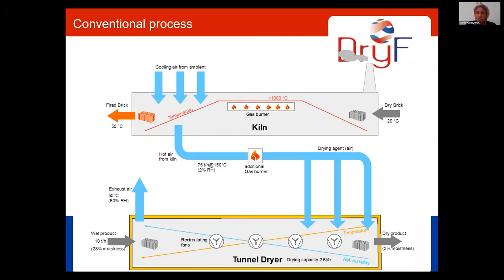We see that the tunnel kiln is nothing else like a counterflow heat exchanger. The product gets heated up to close to 1000 degrees Celsius. And in the cooling zone, we have to get rid of this energy. For sure, this energy could be needed in the heating zone of the kiln, but it is not possible up to now to pick all this energy available to the heating zone.